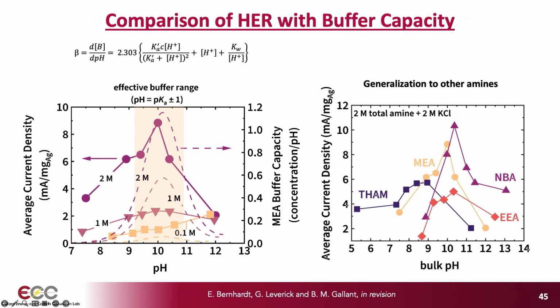And what we wound up learning from this is that the activity of the ammonium is actually very sensitively governed by its buffer capacity, which is mapped, as a kind of theoretical equation, over to our activities here. So it doesn't account for everything, but it really does help to explain why we see a peak at a particular value associated with the pKa of that ammonium.